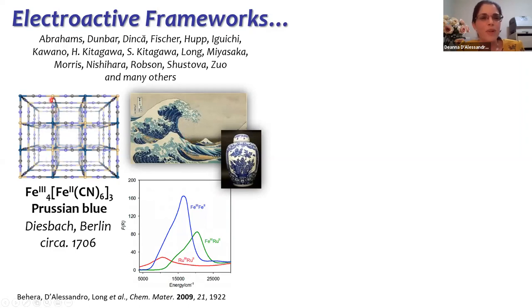This is Prussian blue, which is iron 2 and iron 3 centres linked by cyanide ligands in three-dimensional coordination space. And this difference in charges, the mixed valency, if you like, gives rise to this very important intervalence charge transfer transition, which gives rise to an absorbance in the visible region and gives Prussian blue its beautiful blue coloration. And it's been used, and prized for centuries as an ink and dye stuff. It's used in Japanese artworks like the Great Wave of Kanagawa and Chinese pottery, and even the name blueprint originally comes from the use of Prussian blue.